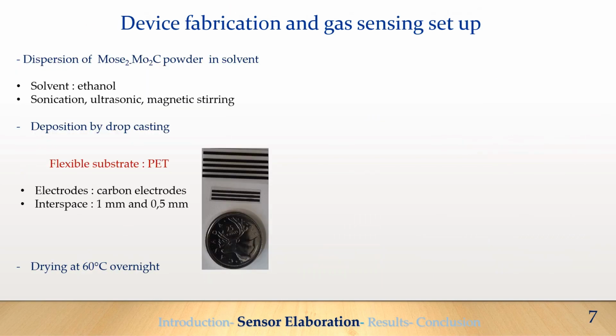Finally, the sensitive material was obtained by dispersing MoSe2-Mo2C powder in ethanol. The suspension was then stirred for 1 hour and sonicated for 1 hour. The thin film was deposited by drop casting on the flexible polyethylene terephthalate substrate, on which carbon electrodes are deposited, then dried at 60 degrees Celsius overnight.